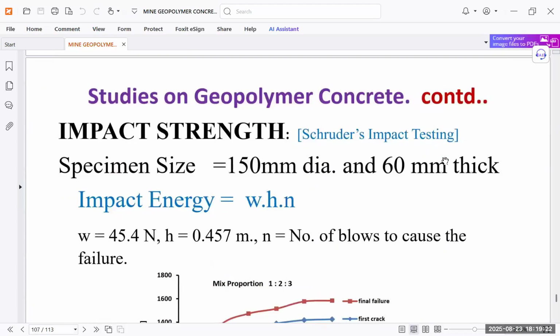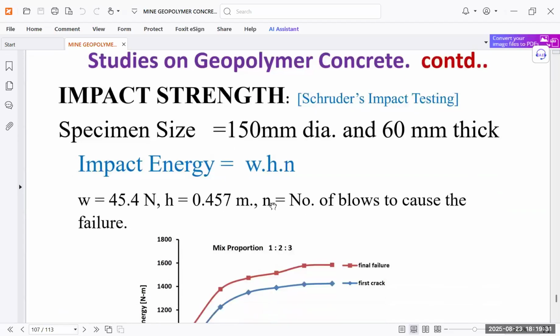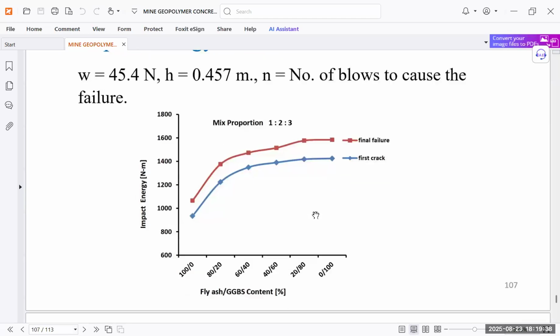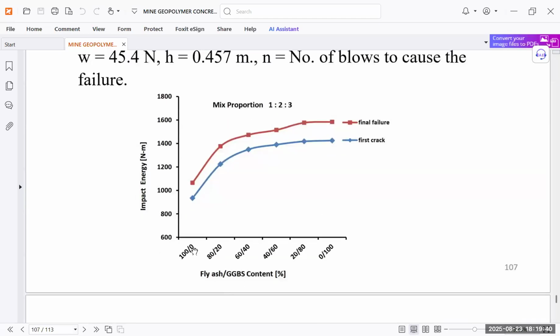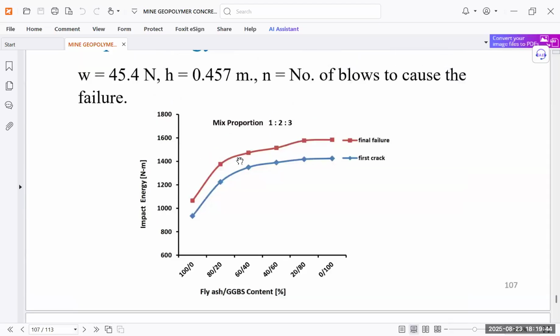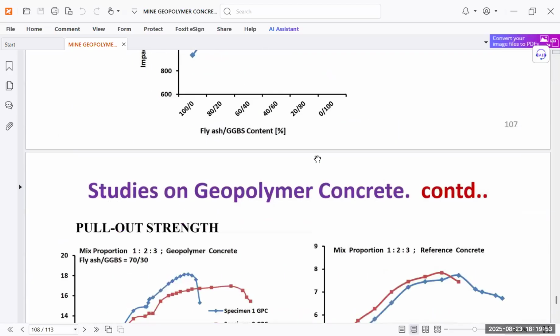Then impact strength is also tested, and this is the Charpy impact testing. Specimen size was taken 150 diameter and 60 thick. Then impact energy in this case, W is 45.4, H is 0.457. Number of blows to cause failure has been checked. Fly ash to GGBS content has been varied 100:0, 80:20, 0:100. Then the next proportion, then the final failure will be something like this. And impact energy and first crack is shown something like this. That has also been checked.